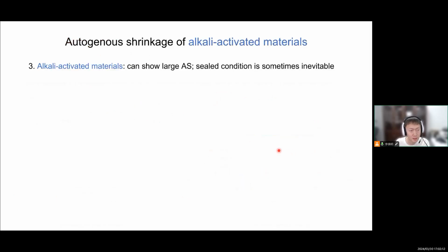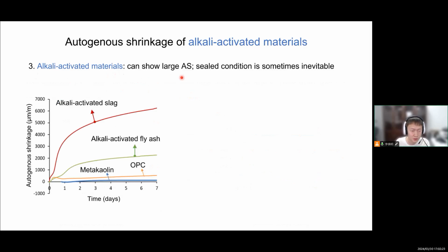shrinkage. The third reason is that we need to be concerned, especially for AAMs, because these materials are special and different from Portland cement. They can show large autogenous shrinkage. The metakaolin system can show low shrinkage, as I will show later, but the fly ash system, alkali-activated fly ash, can already show bigger autogenous shrinkage than OPC. Although the later-age development rate is not high, the total magnitude is not low. And for the alkali-activated slag system, the autogenous shrinkage can be much higher compared to that of Portland cement. So we need to consider this.